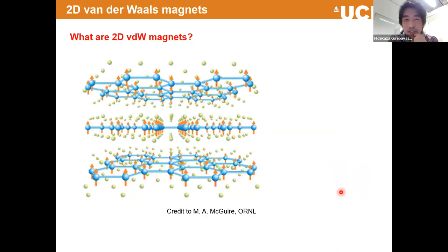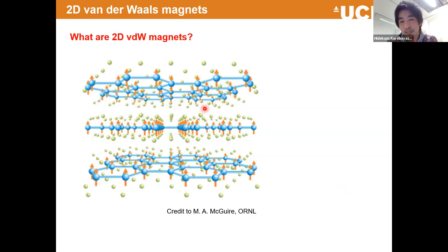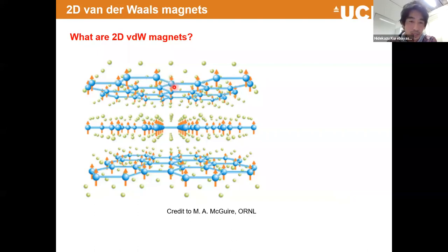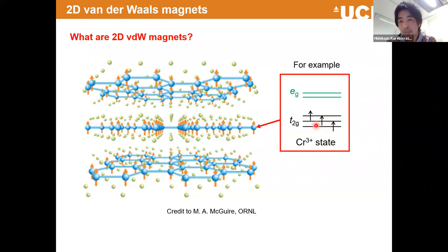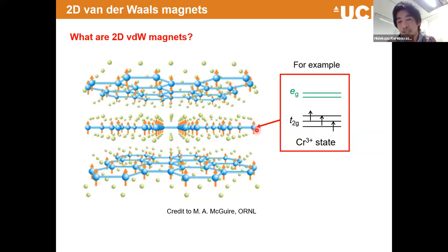I want to give you some flavor of what 2D van der Waals materials are. This is a nice schematic: you have a layered material such as graphene, but the key difference is that it has a spin and localized magnetic moment. We achieve this by incorporating transition metals such as chromium. If the ionic state is 3+, with crystalline or ligand field effects, it creates spin populated into one of the subbands — the T2G band — and because of Hund's rule, you can polarize about 3 µB magnetic moment per atom. That is the ingredient to create magnetic order, and they have reasonably strong exchange coupling.